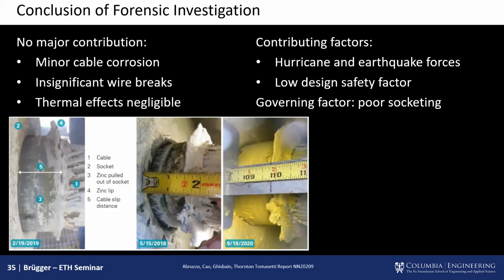Now, since this is sort of a show and tell for civil engineers and structural engineers, what caused the failure? Well, it turns out it was actually just poor socketing. The team looked at corrosion, they looked at wire breaks, there was an acoustic monitoring system, thermal effects of the dish actually raising and lowering. Turns out that was within design specs. Now, what did contribute is that hurricanes did overstress the system at regular intervals, or I would say irregular intervals.